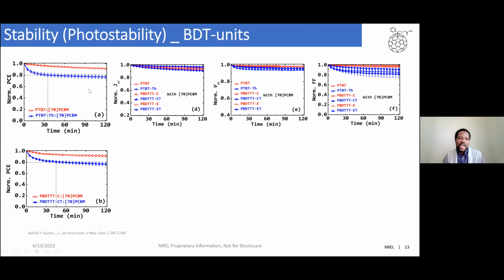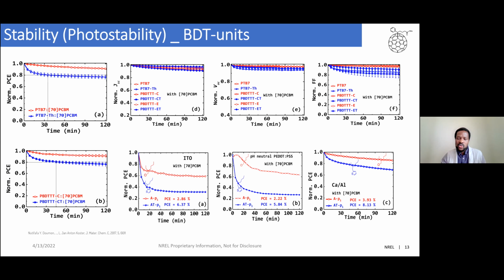So what we also try to do is to look at the interlayers, because the question can be, could this be due to the reaction of this polymer with the other interlayers such as PEDOT:PSS or the lithium fluoride if you are talking about conventional structure, or molybdenum oxide or zinc oxide. So we try to look at that, and we tried various techniques.